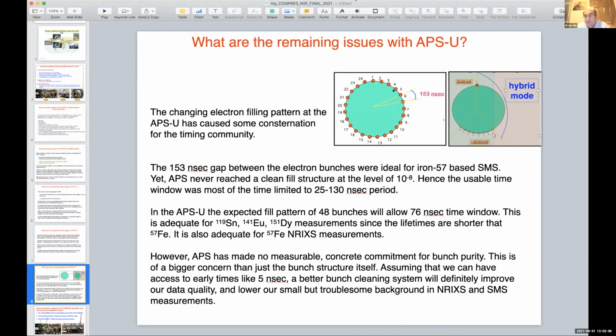APS's injection system failed for 25 years to provide us a clean beam. We complained about this early on for the first 10 years, then I got tired, and every time they promised us to fix it, so I realized that this is a birth defect. And one wonders what kind of birth defects we will have at the APS-U because nobody can guarantee. So we brought this issue up many times that the 48 bunch mode, which will allow us 76 nanoseconds, may also suffer from losing the first 25 nanoseconds, which will be devastating.